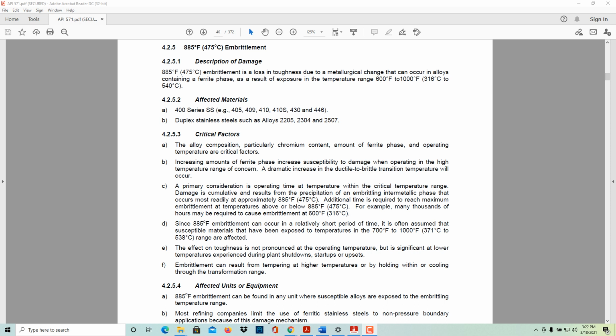885 embrittlement. Description: damage. 885 embrittlement is a loss of toughness due to the metallurgical changes that occur in alloys containing a ferrite phase as a result of exposure to temperatures in the range of 600 to 1000 F. 400 series SS, 405, 409, 410, 410S, 430, and 446 are affected materials. Duplex stainless steels such as alloys 2205, 2304, and 2507 are also affected.